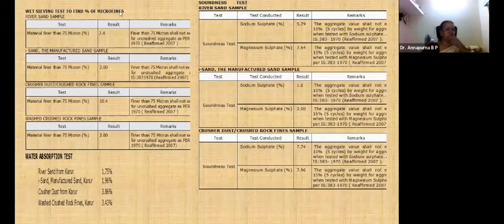Now, the wet sieving test to find the percentage of microfines. This is the wet sieving analysis. It is found that for a river sand sample, the material finer than 75 micron is 2.4%, and for manufactured sand it is 2%. So it is lesser than the river sand. Then the crushed rock dust is 10.4%. After washing the crushed rock dust, we are getting 2% of the material.